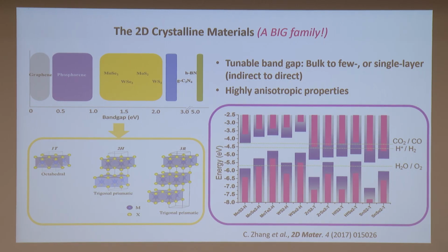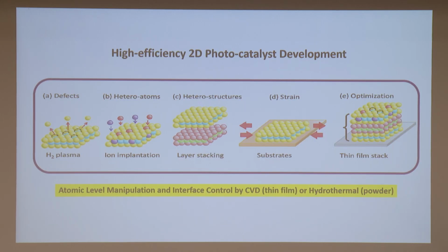And this is just a theoretical calculation of many different 2D materials with their band positions. Okay, so molybdenum disulfide is not bad, and tungsten diselenide and tungsten disulfide, in terms of their band position and band gap, are all in pretty good shape to begin with. And I have to thank Ivan Huang for helping to construct these nice figures. What we can do to play with these 2D photocatalysts: if they are perfect, as I mentioned, CO2 will not bother to react with you, okay? So you have to make something different.